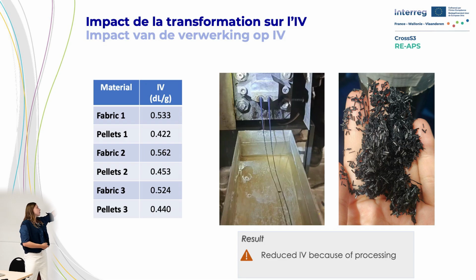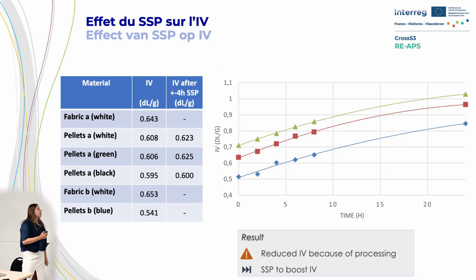So you see that by going from a fabric to a pellet, the IV drops significantly. This is one of the major challenges Isabelle already mentioned. To address this issue, we look at SSP, solid-state polymerization, as a method to restore the intrinsic viscosity. Again, in the table, going from a fabric to shredding, eventually packing, the IV also drops. But what we also see is that by SSP treatment, the IV increases partially. That's already a nice result, because we know that IV is important for the processing later on.